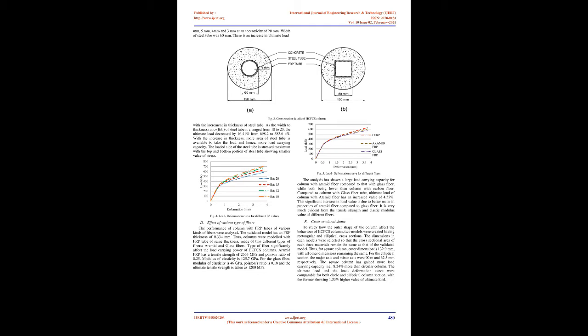The concrete wall and steel tube were modeled using Solid 186 element. It is a higher order 3D 20 node solid element that exhibits quadratic displacement behavior, with 3 degrees of freedom per each node, translations in the X, Y, and Z directions. Since the thickness is less, FRP tube and epoxy are modeled by Shell 181 element. It is well suited for analyzing thin elements. Shell 181 is a 4-node element with 6 degrees of freedom at each node, translations in X, Y, and Z directions and rotations about the X, Y and Z axes.